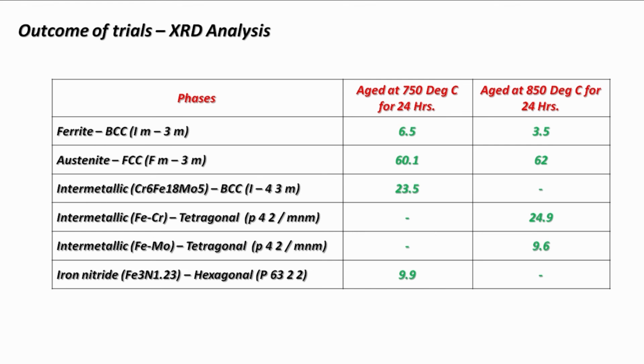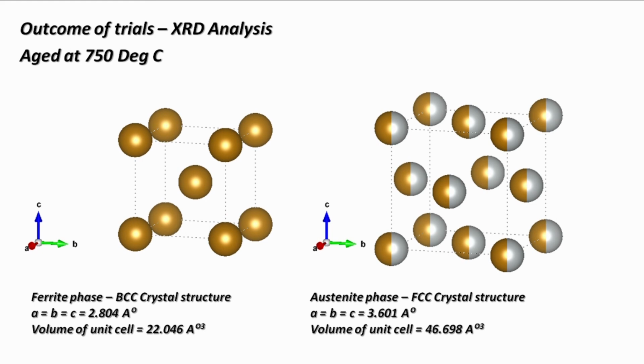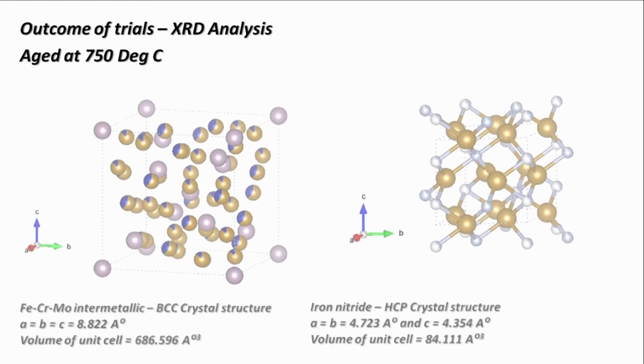So it is very important for us to understand that two phases are forming in duplex stainless steel, which are chi phase and sigma phase, which increase the brittleness of the material, reduce the toughness and produce cracks. So we can see this is the ferrite and austenite which we earlier saw.